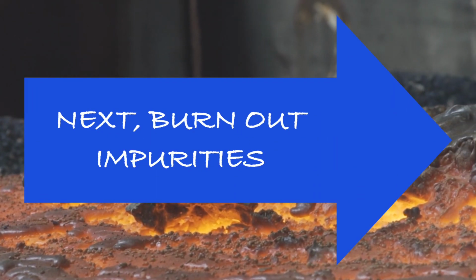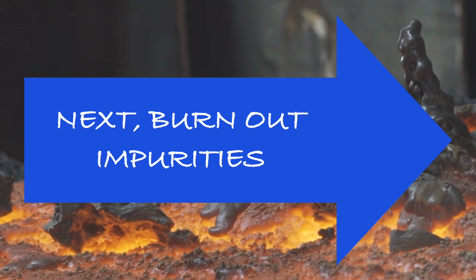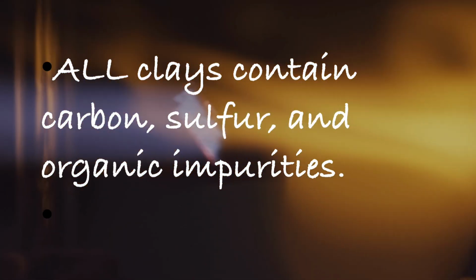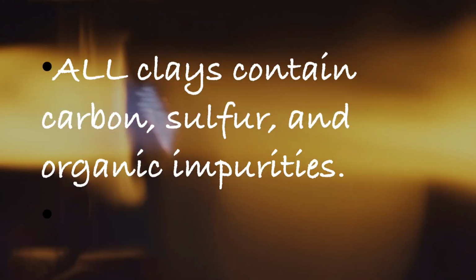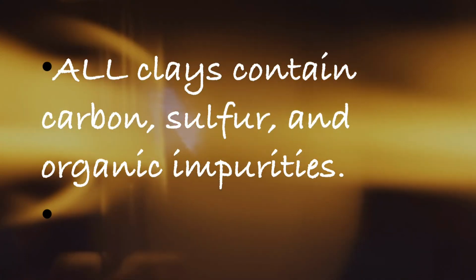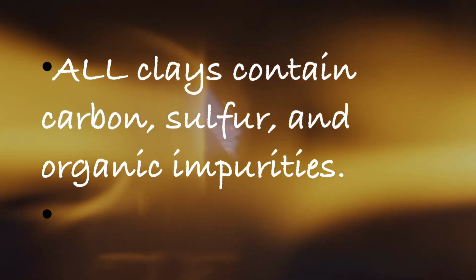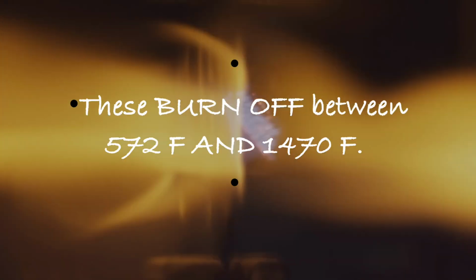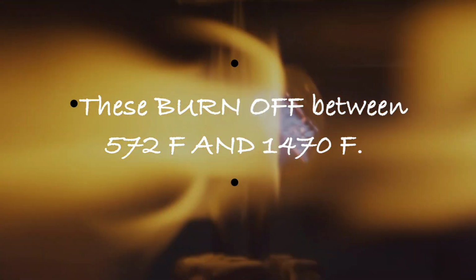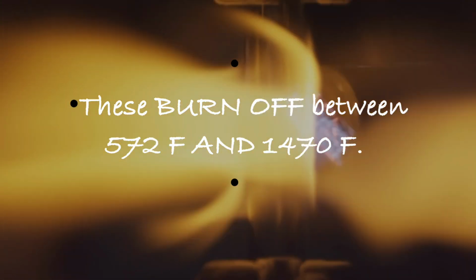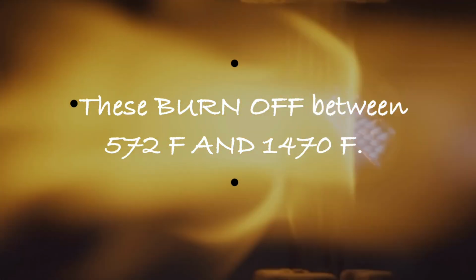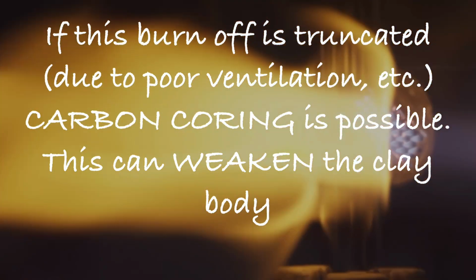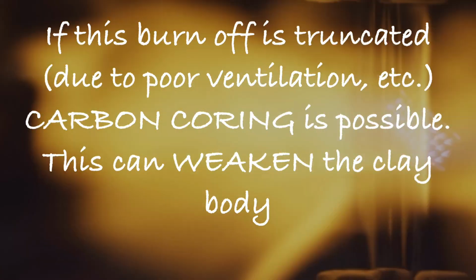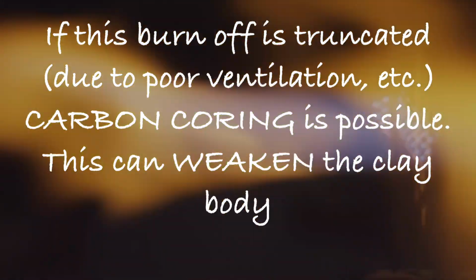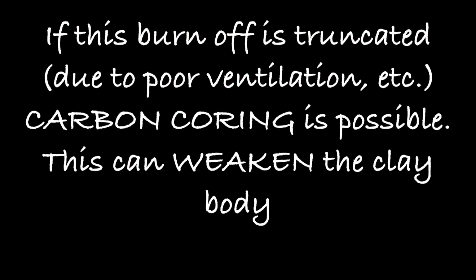The next thing that has to happen is impurities need to be taken out. Clay has a number of impurities. All clay contains carbon, sulfur, and other organic impurities. Dirt, rocks, all kinds of things, even straw. These burn off between 572 degrees Fahrenheit and 1470 degrees Fahrenheit. If this burn is truncated for some reason, maybe due to poor ventilation, carbon coring can occur in your piece, and this can weaken the clay body and leave divots and marks in it.